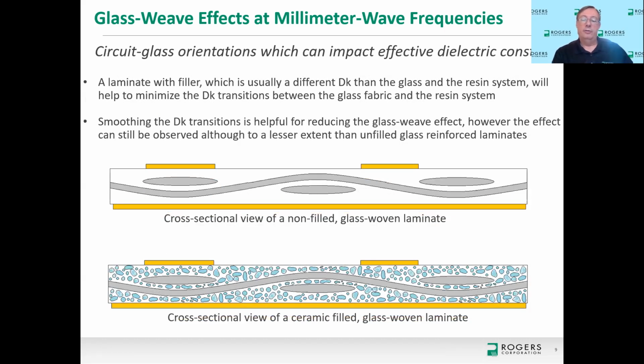Another thing to consider is filler. What I'm showing again on the top picture is our example circuit I've been showing for the last few slides, and it's considered unfilled. So it's just resin and glass only. And then below that is the same type of laminate, except now it's resin, glass, and it has ceramic particles. So for laminates with ceramic filler, the ceramic itself has a different Dk than the Dk of the glass and different than the resin system. The ceramic is actually a higher Dk than the resin system and lower than the glass, and the ceramic particles act like an intermediary to kind of smooth out the glass weave effect. So for open weave glass and using a very highly ceramic filled laminate, the ceramic filler actually minimizes, almost eliminates the glass weave effect. And we'll see that in some of the data that I'll show a little bit later.